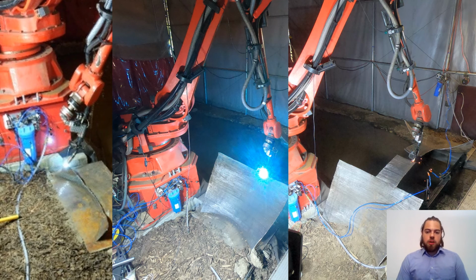The pictures show different time frames during the manufacturing process. On the left side, the first segment is nearly finished. In the middle, the progress of the second section has reached more than 250 layers. Around that time in mid-October, unexpected significant deformations due to thermally induced residual stress occurred. This led to a stop of the construction site. The cross-section of both bridge sides started twisting continuously after the application of 1 or 2 layers, and the welding robot partially missed the bridge when manufacturing the next layer.